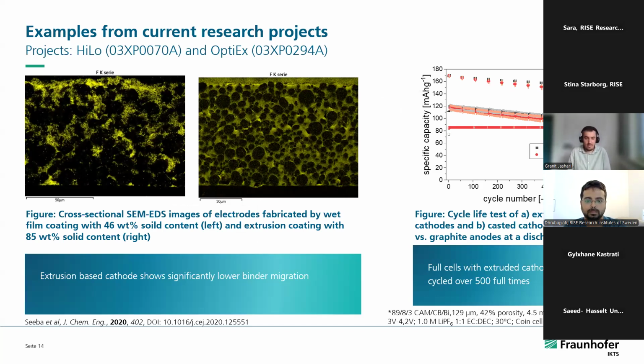We all know that when wet coating technology is used, there are usually a lot of problems with the migration of the binder due to the drying. Since there is a fast drying process, the binder tends to go to the surface of the electrode, and then it's not well distributed through the whole area of the electrode. In this case, we compared two electrodes, one from tape casting and one from the semi-dry extrusion process. And as you can see, in this case it was a PVDF binder.